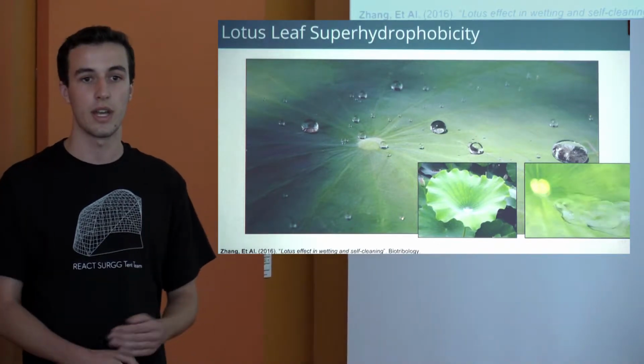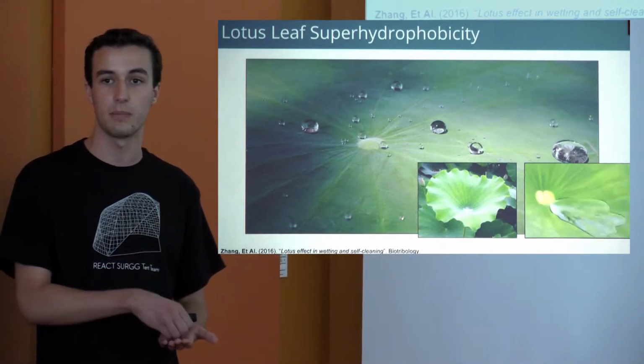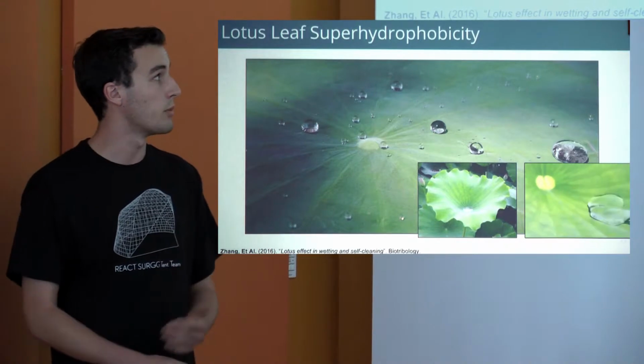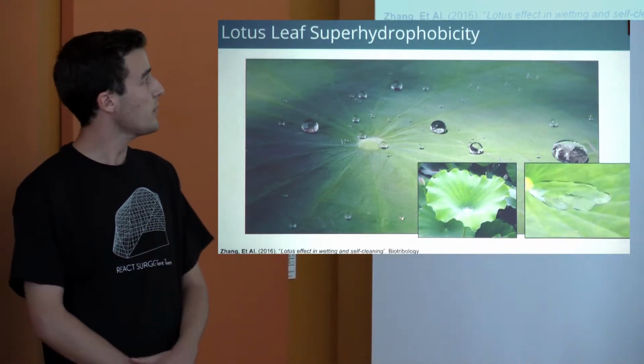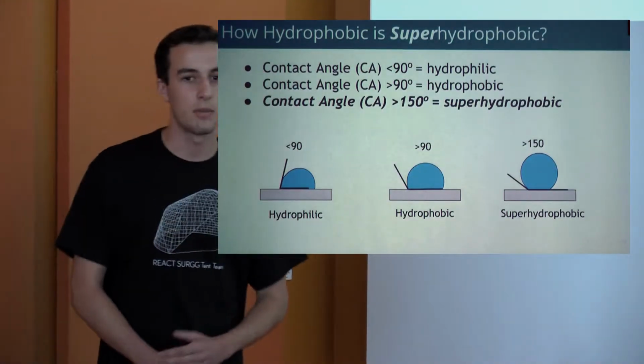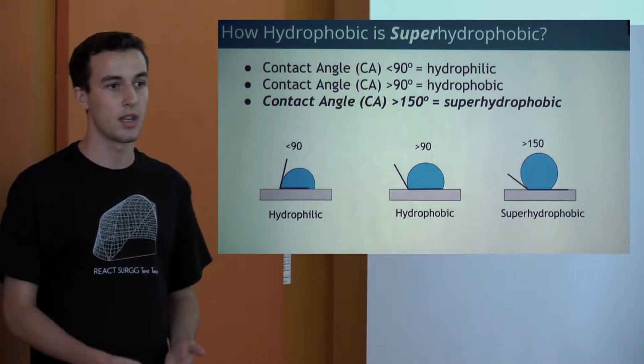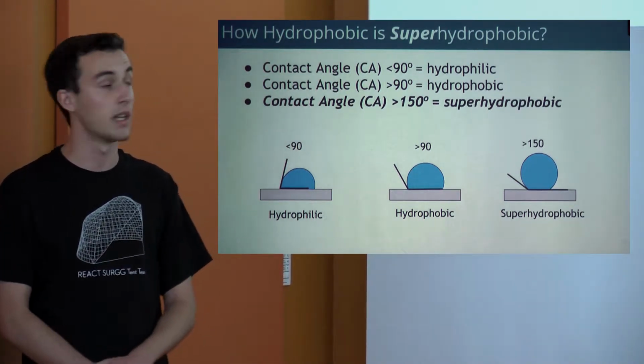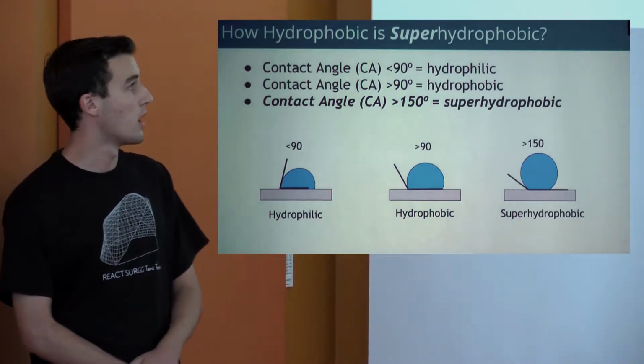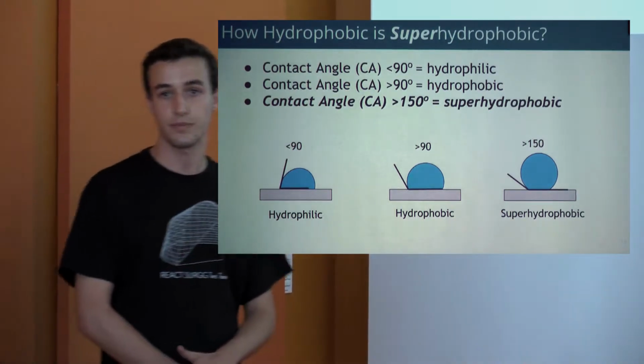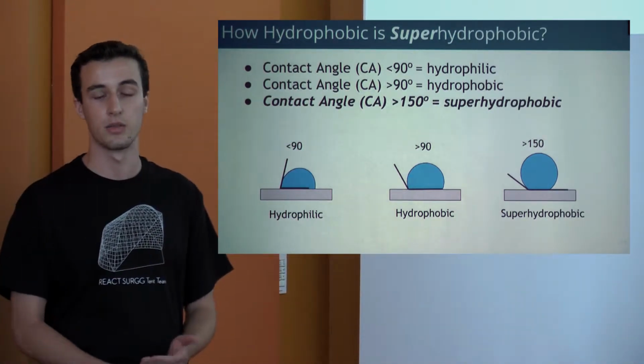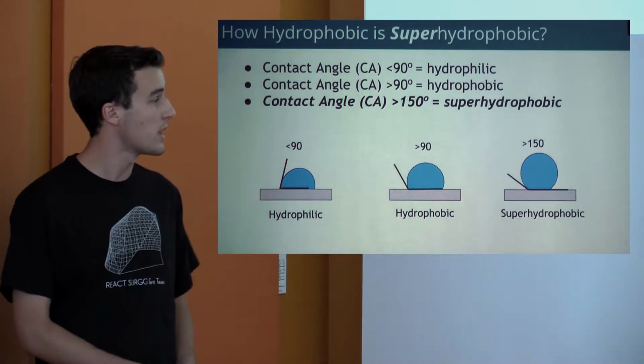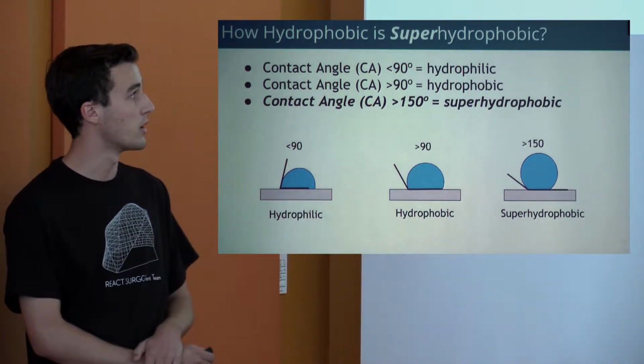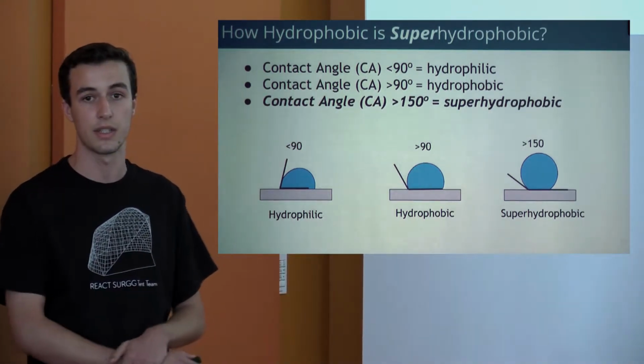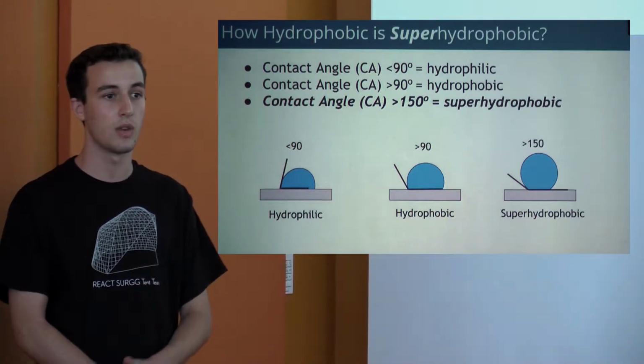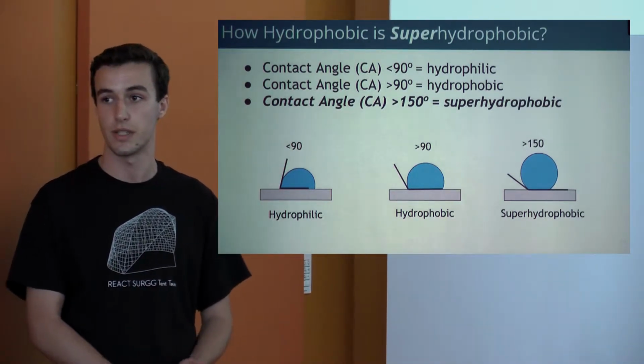So we thought if we could have a surface where the water beads up and it's also slippery, that would be ideal for our tent. So when we talk about how water beads up on the surface, we're talking about the hydrophobicity. And this was measured through a thing called contact angle. So to measure the contact angle, you take a drop of water, place it on the surface, and measure the angle between the droplet and the surface itself. And this angle tells you how hydrophilic or hydrophobic the surface is.